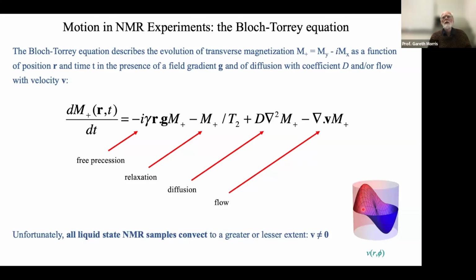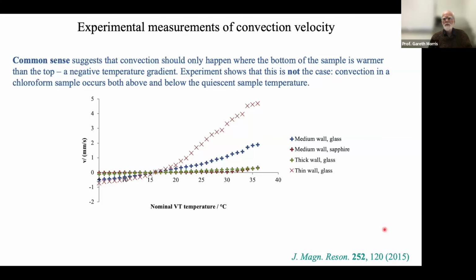Typically, liquid flows up one side of the tube and down the other. But what drives it to do that isn't the sort of convection that we see if we boil a saucepan of water, for example. Because the common sense view of convection is that it arises when we have warm liquid below cold, and the warm liquid says, I want to be on top. And so we get mixing between hot and cold, upper and lower layers. But if that were all that was going on, then so long as our liquid at the bottom of the sample was colder than the liquid at the top, we get no convection.